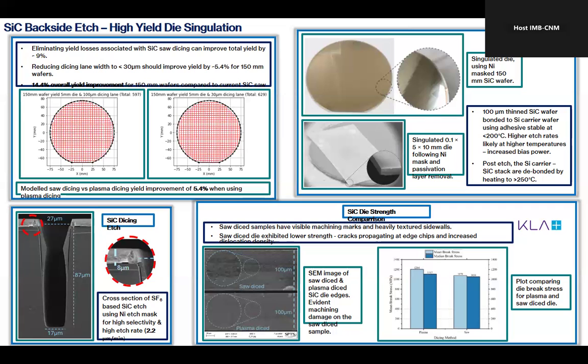What we did instead, at the end of the line, was deposit a nickel mask and use really deep plasma dicing in one of our Synapse tools, I think it was, to singulate the die. We demonstrated a 14.4% yield improvement across the wafer. Also, after the singulation, we improved the mechanical strength of the dies that were remaining, as opposed to the dies that had been diced with a saw. So this is really interesting work for manufacturing of silicon carbide power devices.